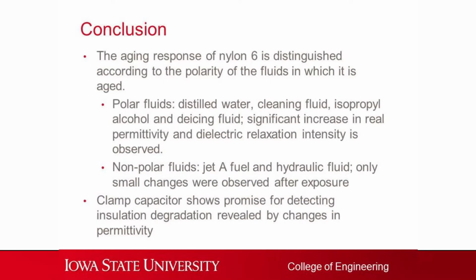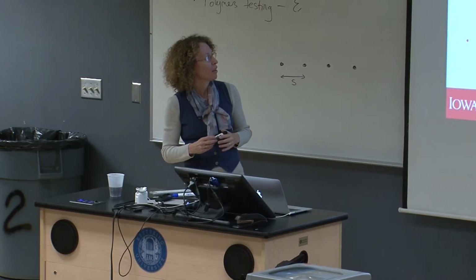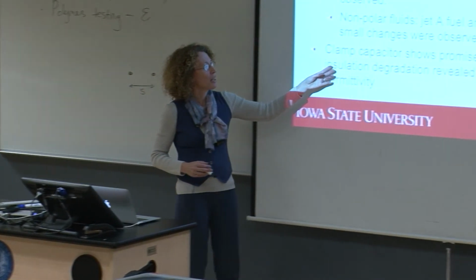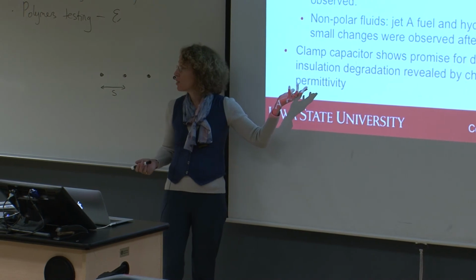Okay, so in conclusion, we were able to show that nylon 6 aging is distinguished according to the polarity of the fluids that you put it in, either water-based or hydrocarbon-based. And in addition to that, our clamp capacitor shows that it's promising, I think, for detecting degradation through changing permittivity of the material.